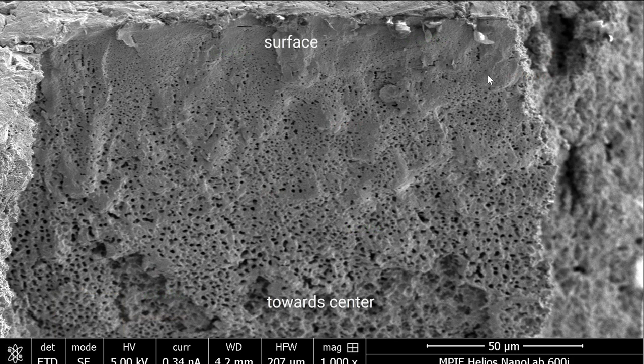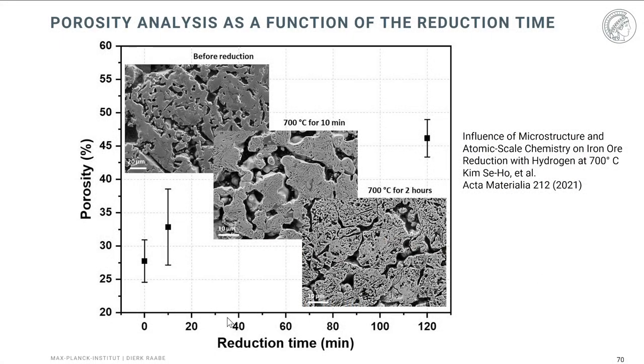This shows a view graph from a single crystalline wüstite from the surface towards the center, and you see a gradient in the porosity. For the reactions close to the surface of the oxide, you see that the material can really leave the free surface. In the center, however, the mass balance leads to a massive porosity formation. This also changes as a function of the reduction time, as you see here in this view graph, with a couple of snapshots at 700 degrees centigrade.